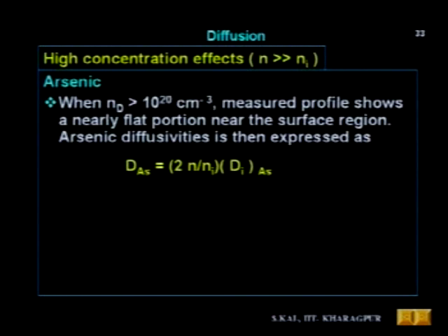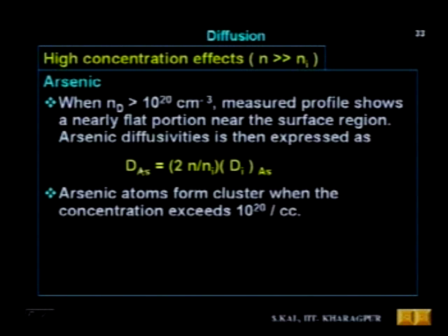Nd is the donor concentration, which is basically here n, and D_As is arsenic diffusivity, and D_iAs is arsenic diffusivity at intrinsic carrier concentration, the arsenic diffusivity in intrinsic level. So now D_As is equal to twice n by ni D_iAs. Now if you increase n, that means doping concentration is greater than 10 to the power 20, then we will find D_As increases. That means diffusivity increases in case of arsenic. So arsenic atoms form cluster when the concentration exceeds 10 to the power 20 atoms per cc.